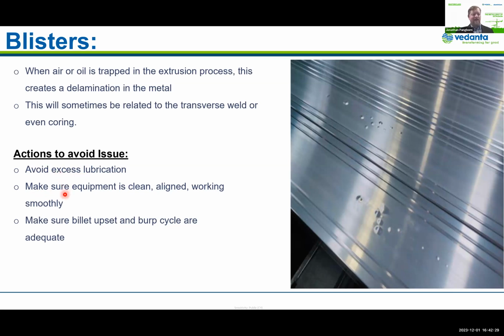And in general, making sure equipment is clean, aligned, and working smoothly, because there'll be less temptation to have excess oil or lubrication in the process, as well as we'll have a consistent burp and a more consistent shear, and we're more likely to have a repeatable process. And I do mention here the billet upset and burp cycle, making sure that those are set up properly, so we're removing all the air at the beginning of the process.